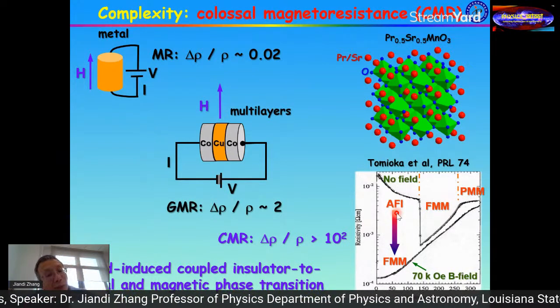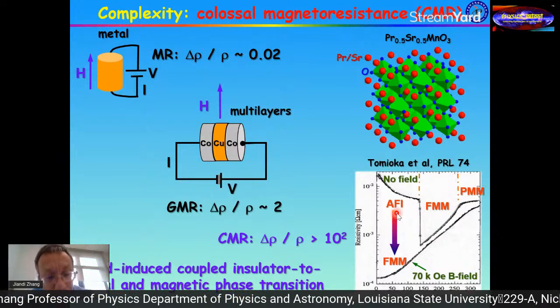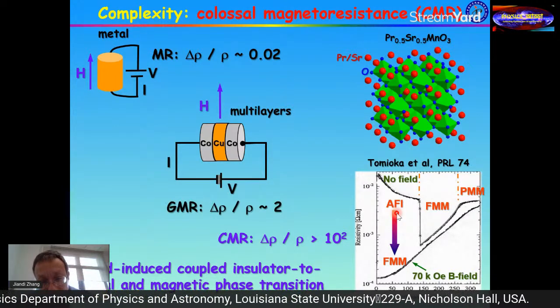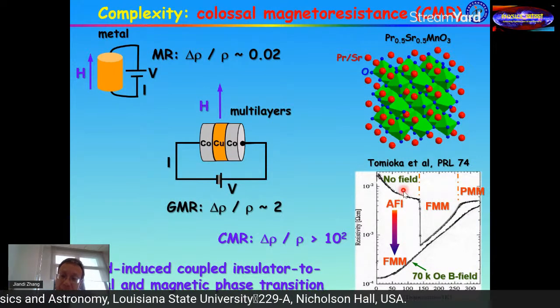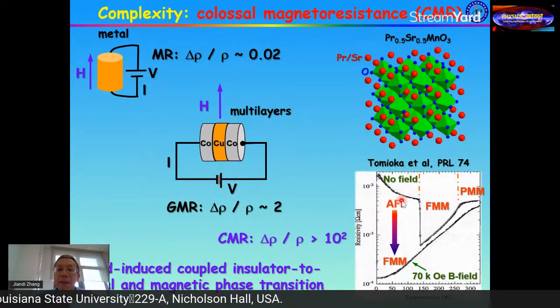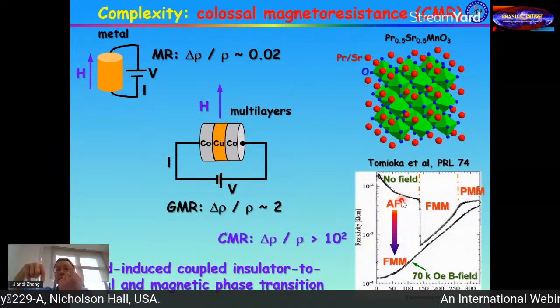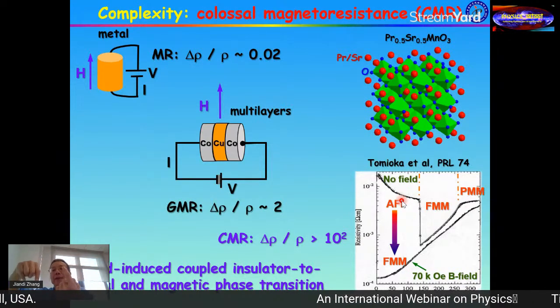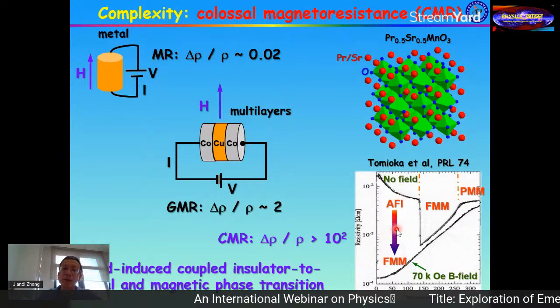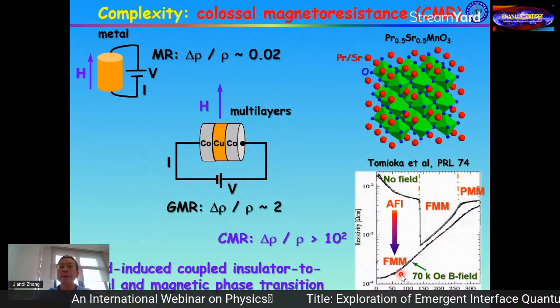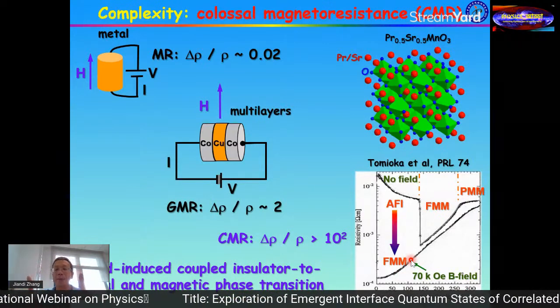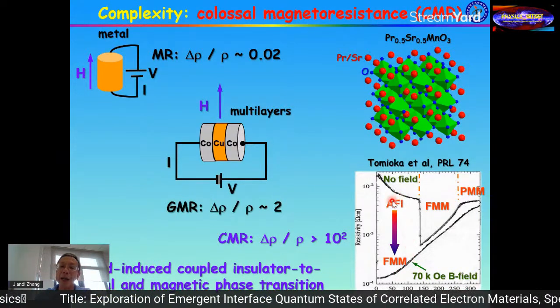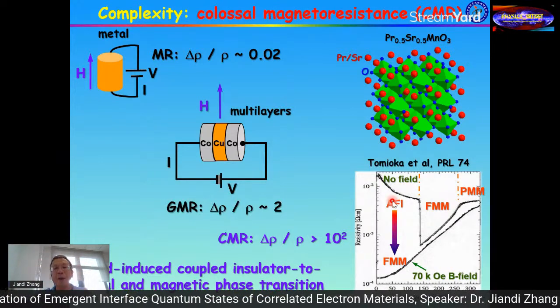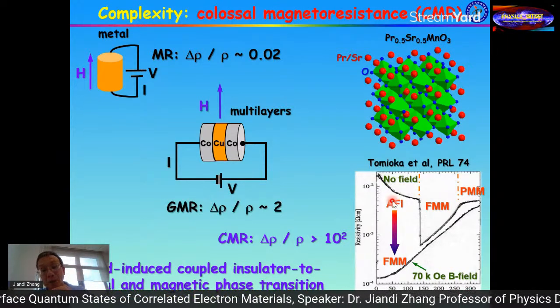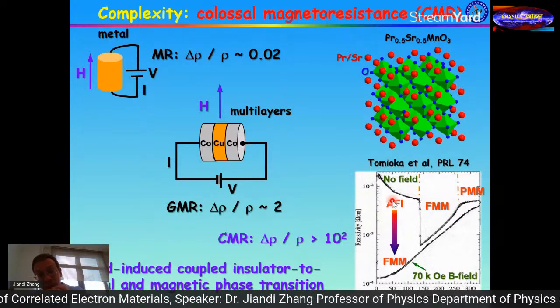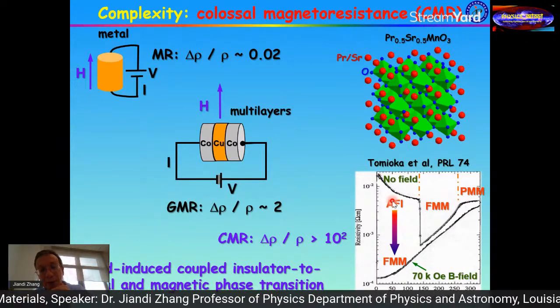So this is the so-called field-induced coupled metal-insulator transition and magnetic phase transition. Because in the insulating phase, the system is antiferromagnetic. It means your spin near my spin are anti-parallel. And when you apply enough field, you turn into a ferromagnetic metal. Okay? From an antiferromagnetic insulator to a ferromagnetic metal. So it's a coupled electronic and magnetic transition, simply by applying a giant field in there.